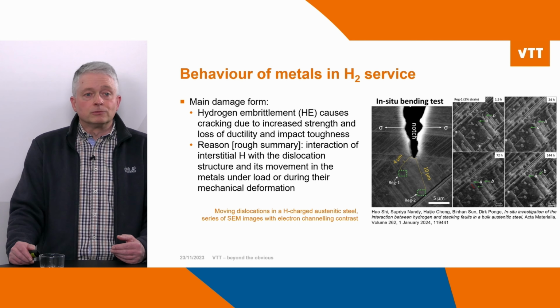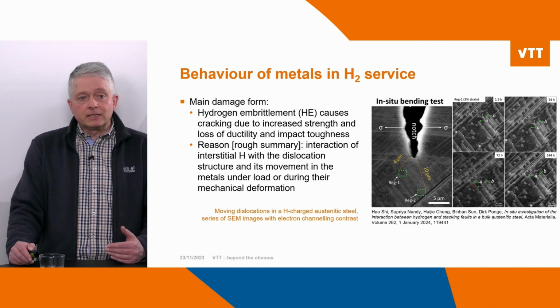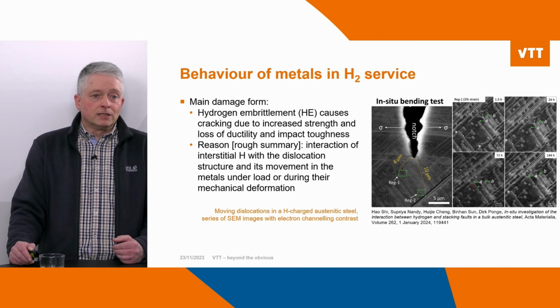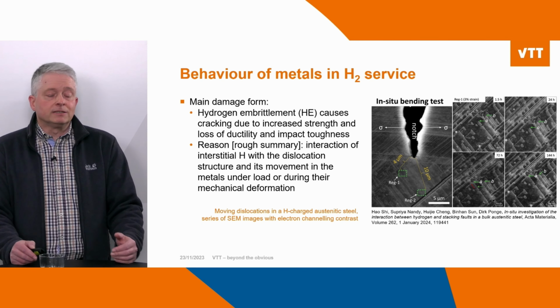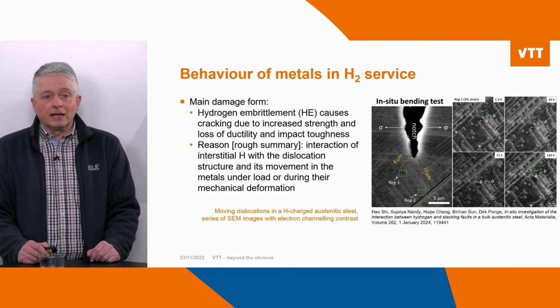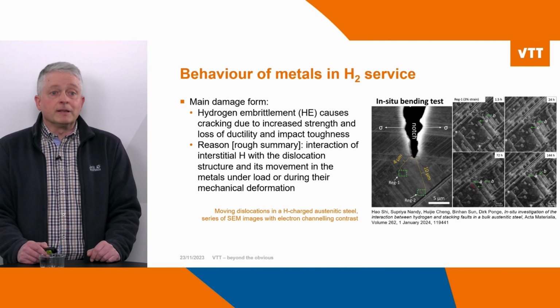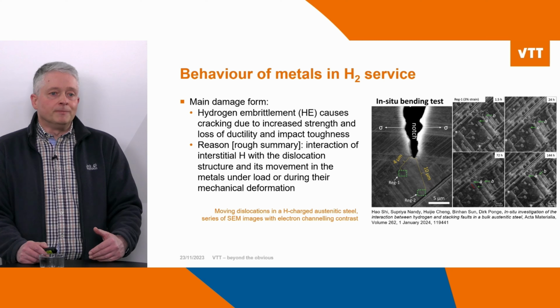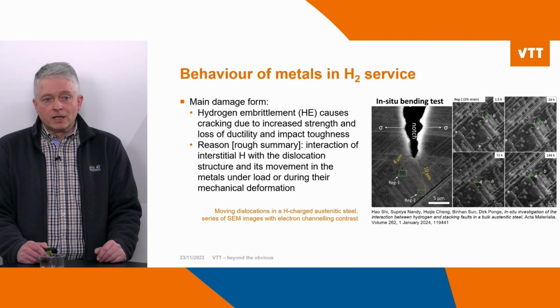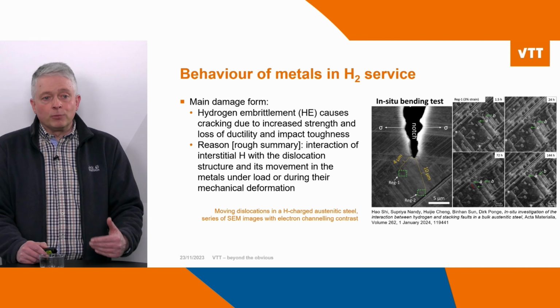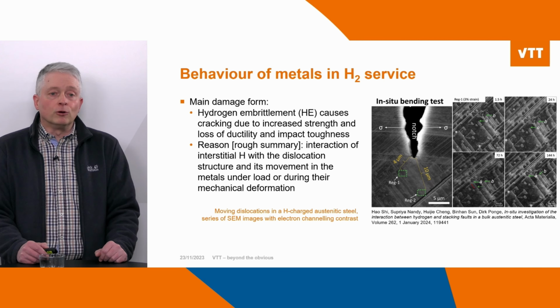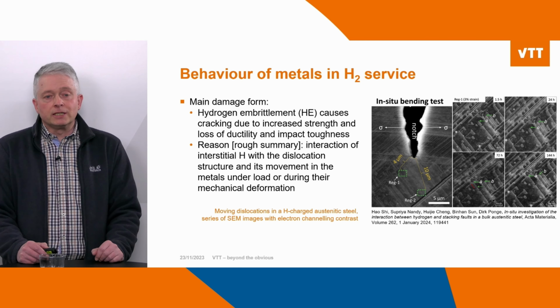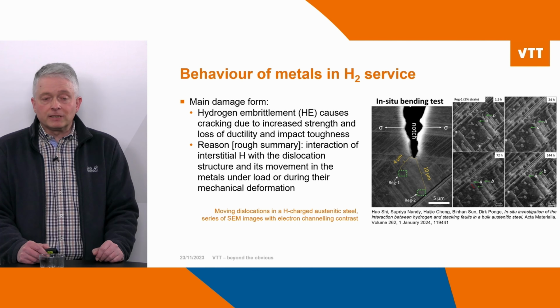This often leads to cracking because the strength of the material is increased and the material loses ductility and impact toughness. The reason, roughly summarized, is that the hydrogen interacts with the interstitials, and interacts with the dislocation structure and its movement. So this is important, especially when metals are under load or are deformed. On this microscopic picture, you can see a series of electron microscope images with electron channeling contrast, where you can actually see dislocations moving.